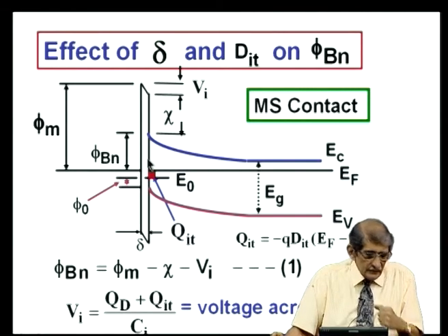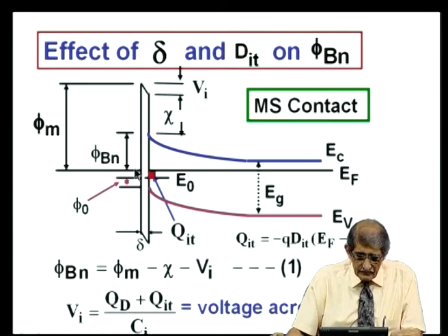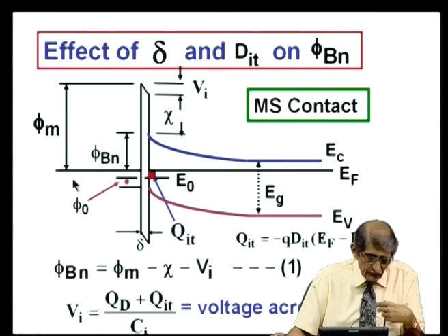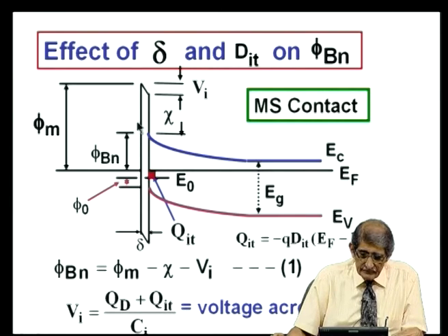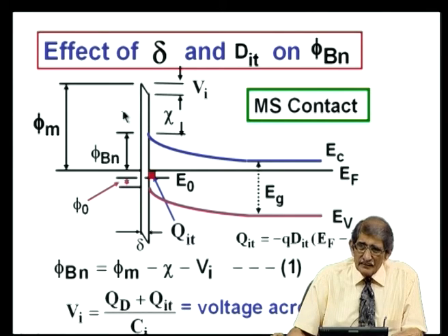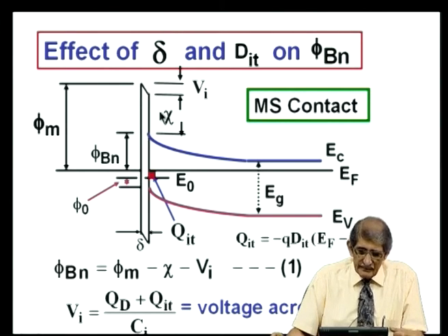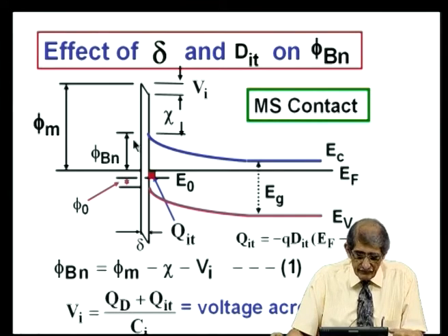So, let us see what happened. This is the Fermi level and there is a vacuum level, that is phi m. Now, this layer is very thin, so if the electrons have energy above this, they can tunnel through that 1 nanometer or less. So, this is still the phi_bn, where the conduction band is coming into this point. There are a large density of states available here, electrons here can cross into this. Similarly, electrons can cross from here to here. When we discussed Schottky-Barrier theory, we said there is zero there and it was just a barrier of states available there.